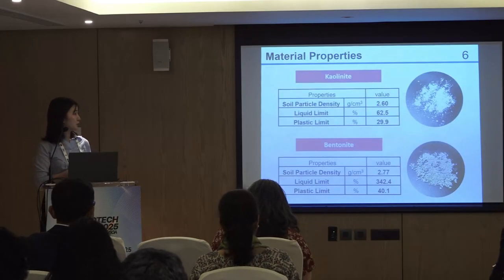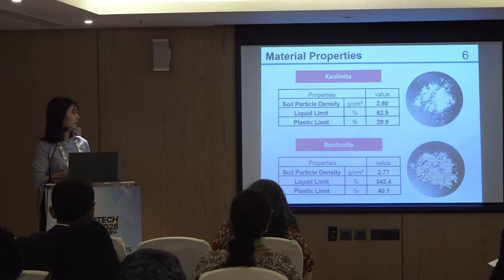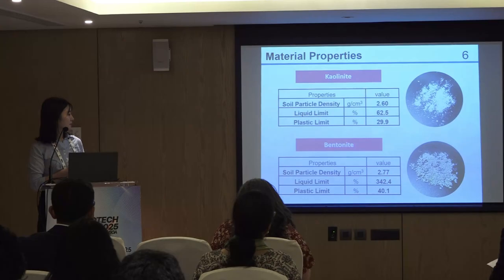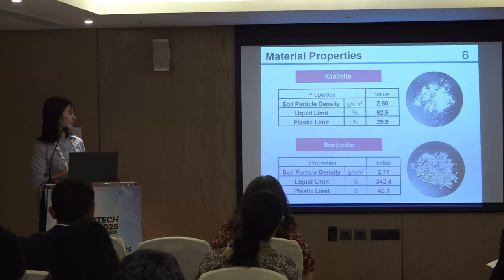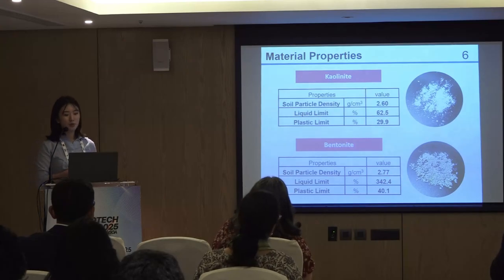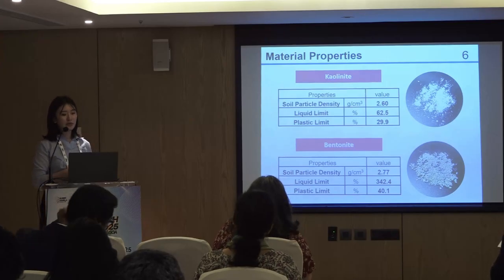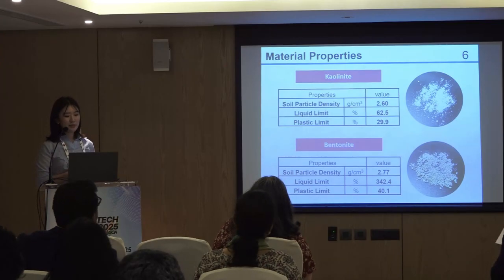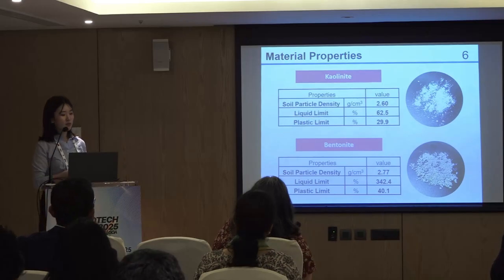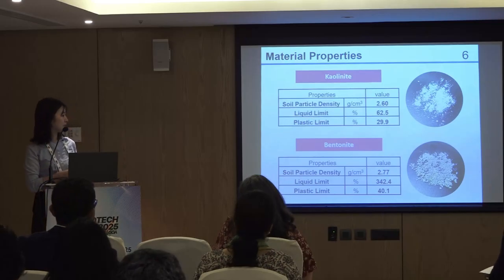These tables show the material properties of kaolinite and bentonite we used. The liquid limit of bentonite is 342.4%, which is extremely high compared to kaolinite. This means bentonite in this study has quite strong swelling and water retention capacity.